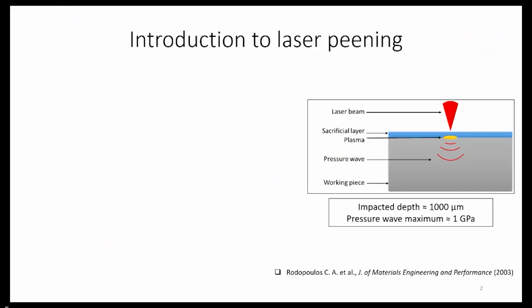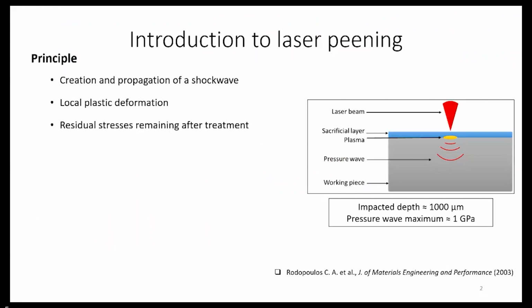First I will introduce you to laser peening, which is a technique already used in the industry, which consists in focusing a laser beam on the surface of the metal we want to process. Thanks to a sacrificial layer, the plasma is confined on the surface and creates a pressure wave which propagates below the irradiated surface. This propagation creates a local plastic deformation, which results in residual stresses remaining after the shock wave.